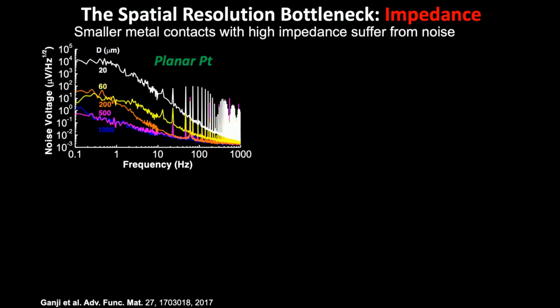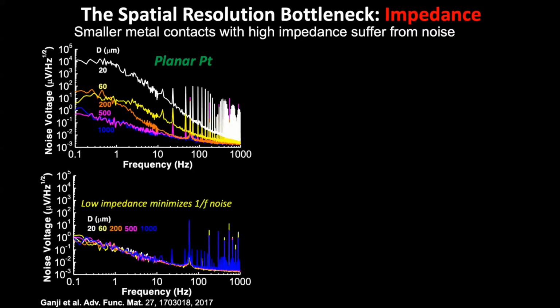And this plot right here shows the noise voltage as a function of frequency in order to bring what I mentioned on the previous slide to data. The noise voltage is plotted here for different contact diameters going from 1 millimeter all the way down to 20 microns. And we can see that at low frequency, the 1/f noise dominates. We have an increase as a function of 1/d squared in the noise as we go to small contacts.